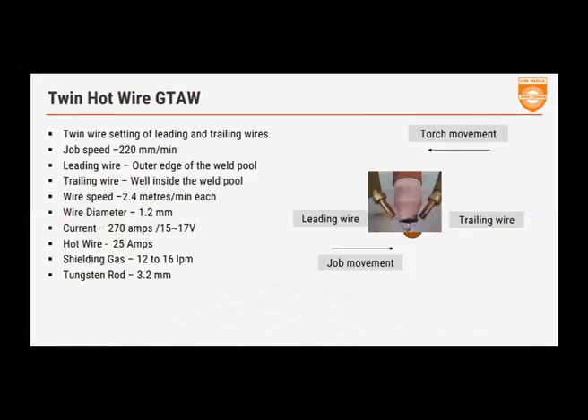Now, if you were to do a twin hot wire, what does that mean? You would have twin wires. The torch is fixed, for example, on a boom, and the job is moving in this direction. Say it's a circular seam and you are rotating the job. This would be the leading wire that is coming into the pool. It would just be at the outside of the weld pool. This would be the trailing wire, which would be getting inside the molten pool already. So it would be well within the center of the pool. This is how the setting would be.